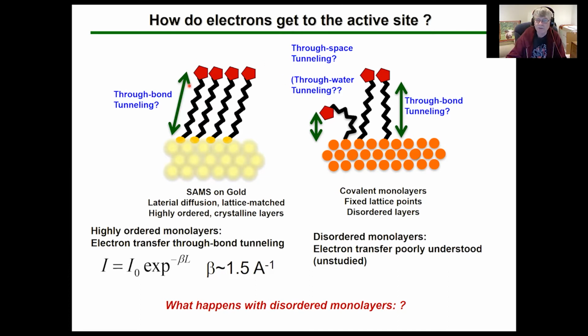And so when one does these molecular layers on gold, they are so-called self-assembled monolayers because the alkyl chains of the molecules dictate the distance between the layer, and things can be well ordered because there's a good registry between that optimal packing distance and an intrinsic bond separation of the surface atoms. On the other hand, the diamond lattice is really tight. And in fact, the carbon-carbon bond distance on diamond is less than the diameter of an alkyl chain. Therefore, it's not possible to functionalize every diamond site with an alkyl chain. And in fact, you can probably only functionalize about 1 out of 6, because once you functionalize one carbon atom, the immediately adjacent neighbors are probably blocked by steric effects.